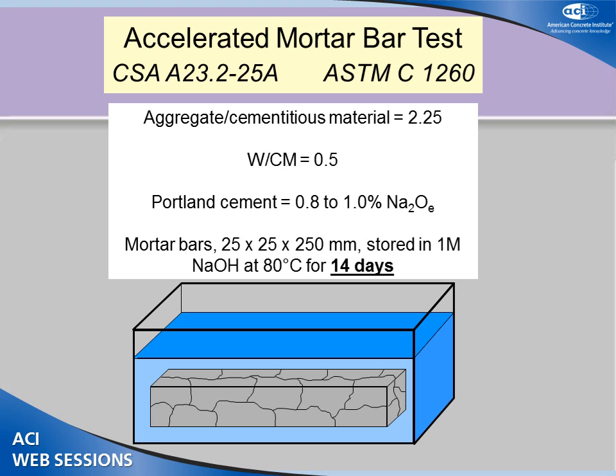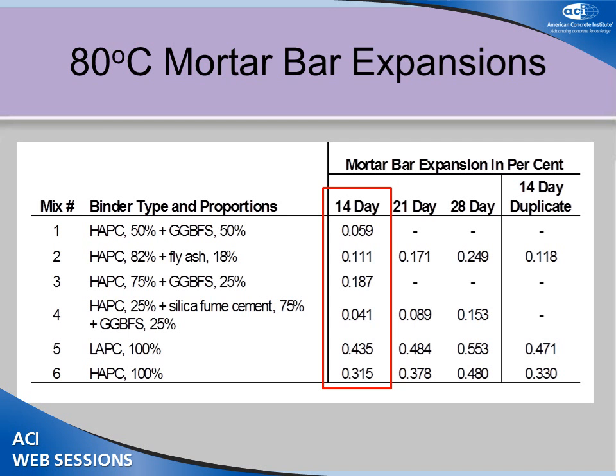So you already know about this test, the 80-degree test. The 14-day expansions for the 6 mixes are shown there. And based on those predictions, the 50% slag mix and the ternary blend with silica fume and slag would pass the test. You can see that both the low-alkali and high-alkali cement have high expansions because the alkali level of the cement in that test has no impact, because you're throwing it into a 1 normal solution, so there's no impact of the alkali. And of course, 25% slag and the 18% fly ash weren't sufficient to keep it below 0.1. And just for fun, we measured a bunch of them out to 28 days, even back then.